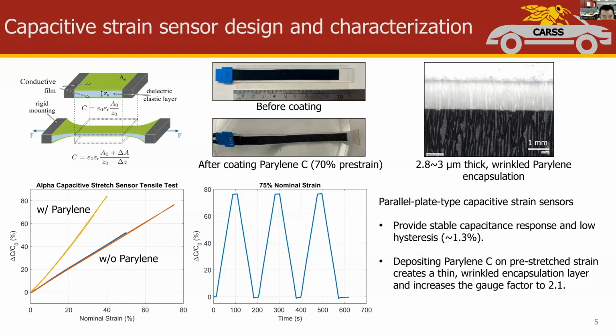To measure the strain at an organ, we decided to use stretchable capacitive strain sensor with the standard parallel plate design. As you can see in the first figure, when the sensor is stretched, the overlapping area between the two conductive electrodes will increase, and the thickness between them will decrease. Thus, the total capacitance between the two electrode layers will increase with the increasing strain.